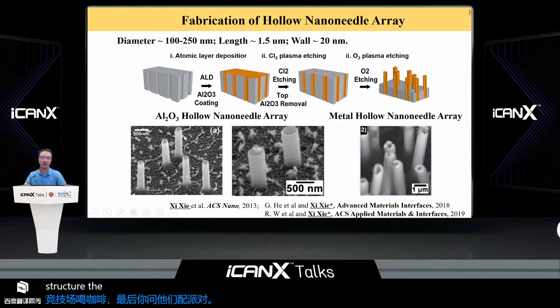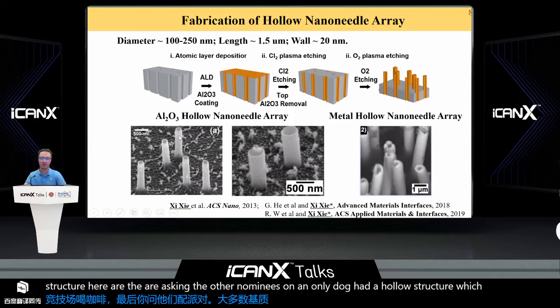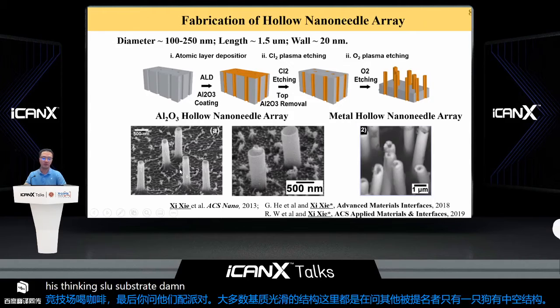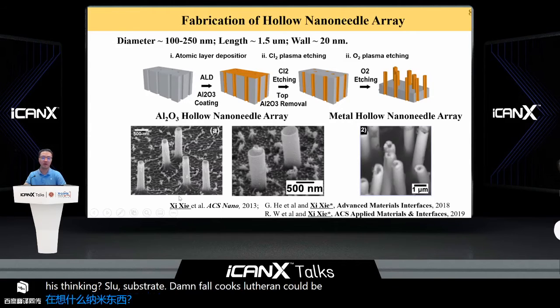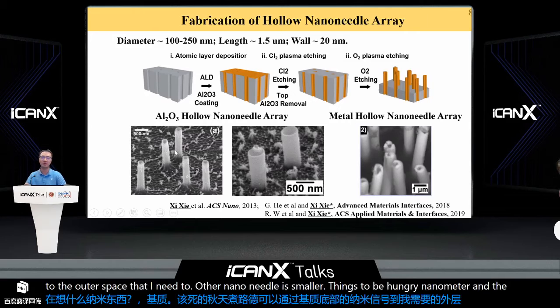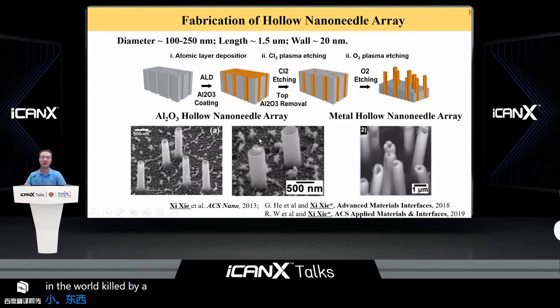Here are the SEM images showing the structure of the nano needle. The nano needle has a hollow structure with a nano channel extending through the substrate. Therefore, liquid solution can go through the nano channel from the substrate bottom to the upper space. The diameter of the nano needle is smaller than 300 nanometers, and the geometry can be well tuned. For example, we can modulate the diameter, height, and distance of the nano needles.